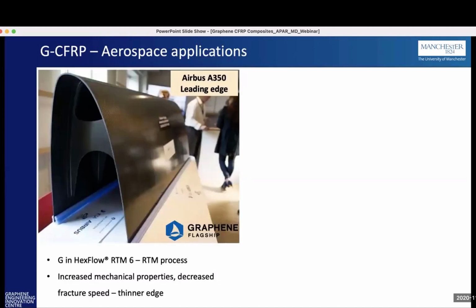Aerospace applications: one which I'm sure most people have seen is the Airbus A350 leading edge. This was part of the Wing of the Future project with Graphene Flagship. It used a Hexflow RTM6 resin system, to which they added graphene, and put it through an RTM process. They managed to increase the mechanical properties and also decrease the fracture speed of the component when it was in use. By increasing the mechanical properties, they were also able to use less material, which gave it a thinner edge. The component itself was a lot thinner, a lot lighter, and a better product altogether.